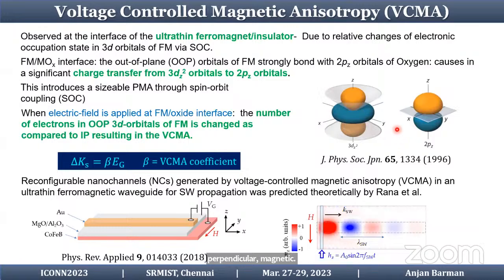Now, if you apply an electric field, the electron occupation in these two bands will change, and as a result, it will change the anisotropy. So there will be an electric field control, or voltage control, of anisotropy in this system, which is characterized by this coefficient beta, the VCMA coefficient. So this is known, and we have done various experiments on that.